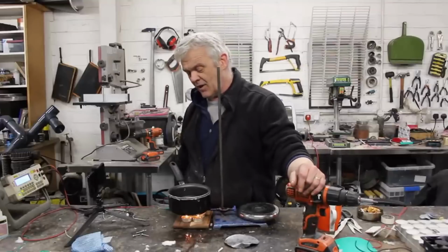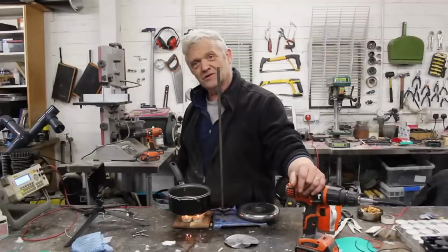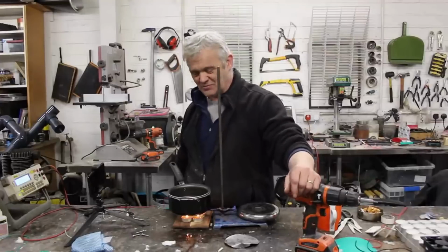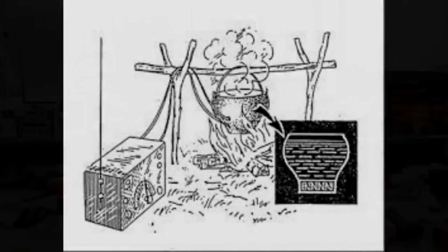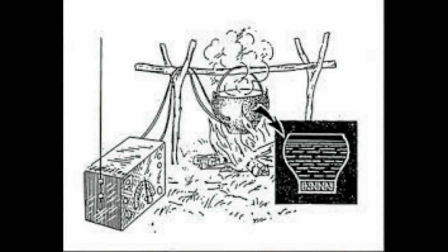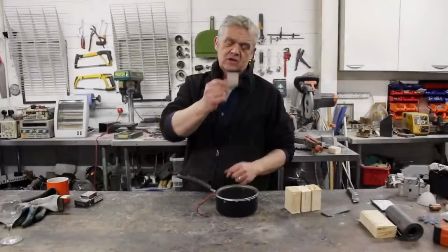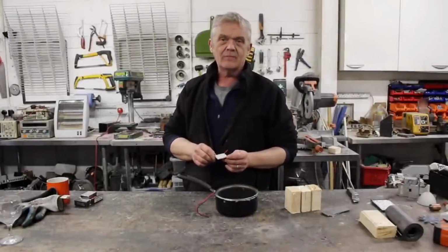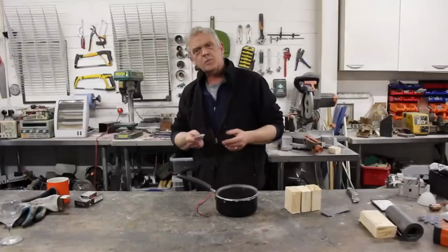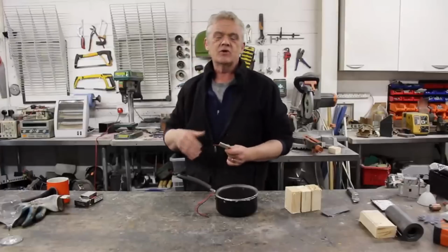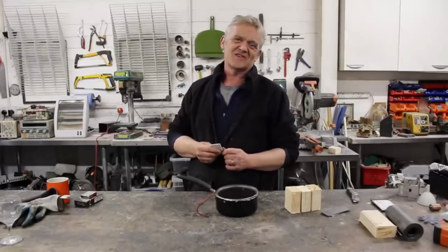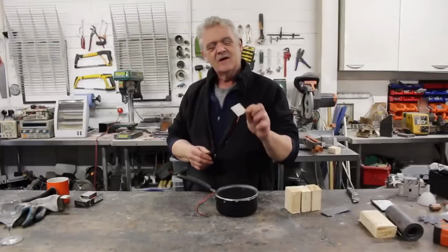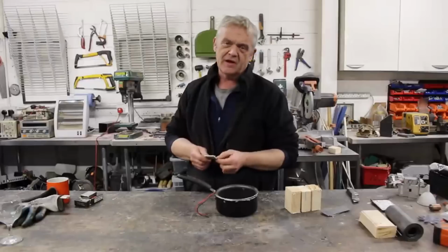But we got our modern miracle working, and it worked and lit a light and put out some power and maybe enough to charge a mobile phone, so it was pretty cool. And I was disappointed with it on a number of levels. One of them is that in there are some of these, which are a modern day Peltier stroke Seebeck device, and they're disappointing. They're disappointing because of the limitations on them. You can't go over 200 degrees centigrade or you pop it. And I know that because I popped a few trying it. So they just won't work above that kind of temperature.